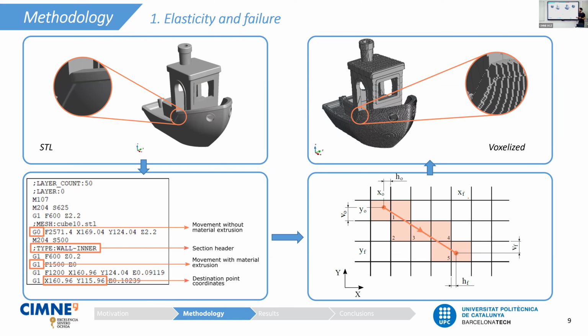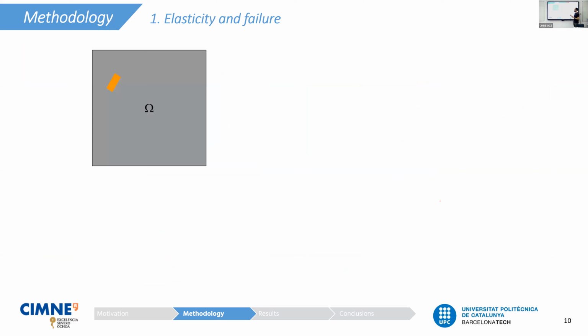However, there's a problem with this strategy, and that is that in order to capture all the geometrical complexities of this component, we have to define a very, very small element, which implies a lot of elements and therefore a very expensive simulation. In order to solve this problem, we perform an adaptive mesh refinement, meaning that we coarsen the elements that are far from the parts of the geometry that are more complex. We coarsen the elements, and therefore we reduce the total number of boxes that we analyze.